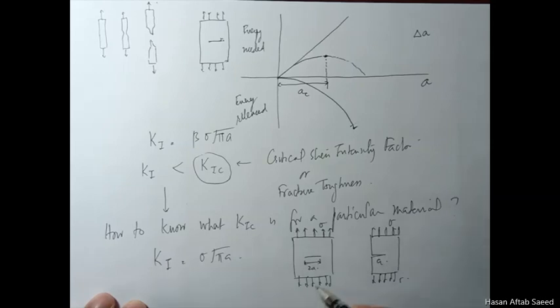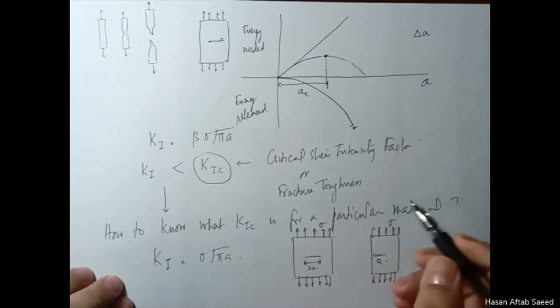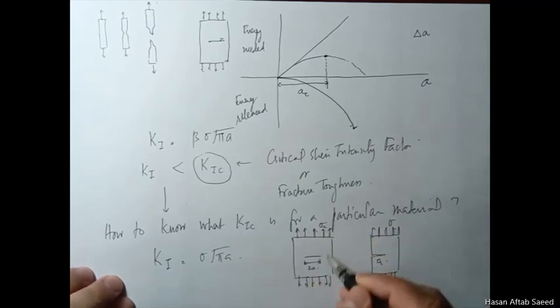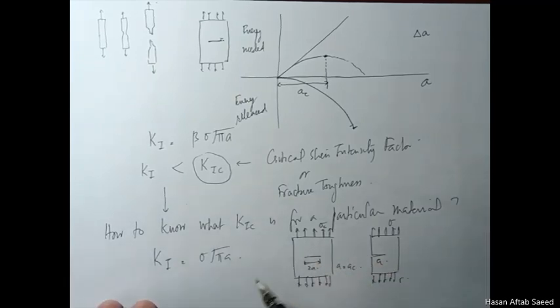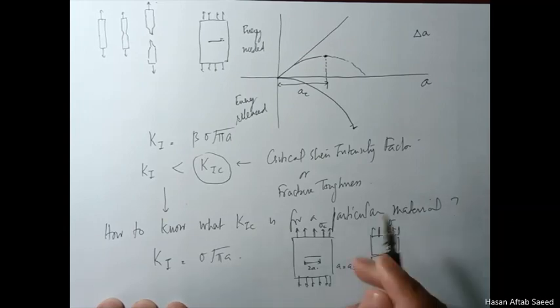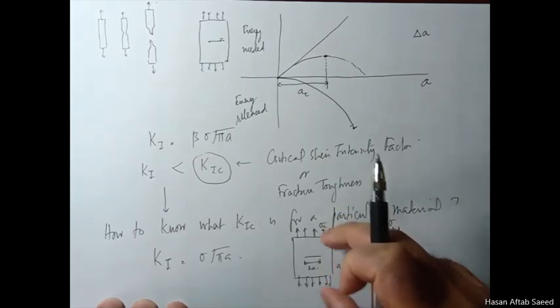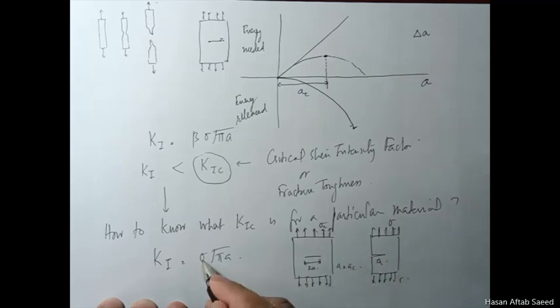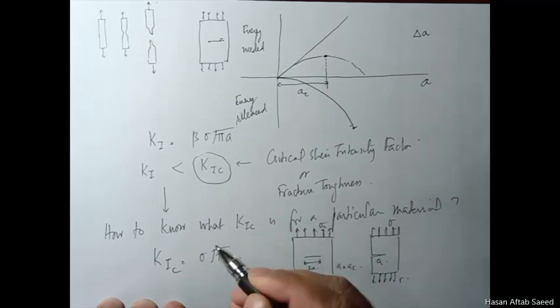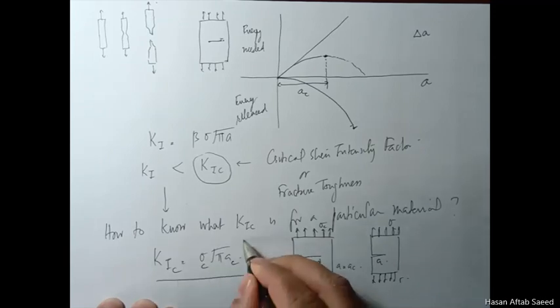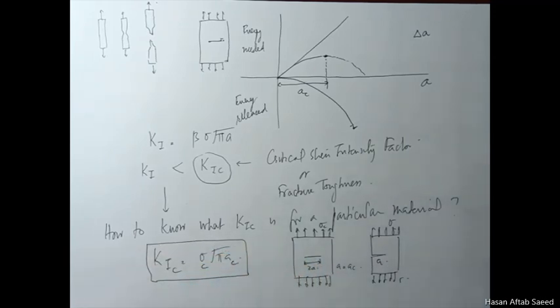And then you know that at that point, the energy release rate was higher than the energy required to increase the length of the crack. Because before that, it was not extending, now it extended. So at that point, this will become sigma, and this A will become AC. So when you use a certain crack length, put in the value here, and for the stress that makes this crack run away, put the value here, and whatever you get here will become the critical stress intensity factor.